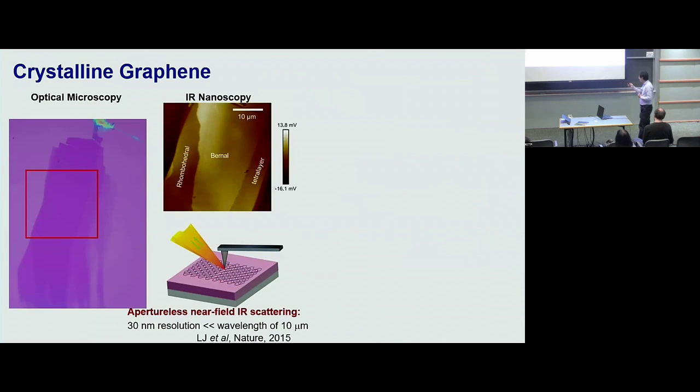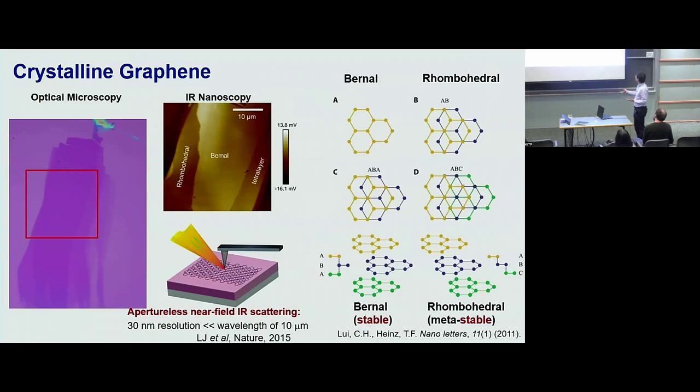And these are 2 different stacking orders of graphite, right? Specifically, the Bernal stacking corresponds to the so-called AB, AB, AB stacking. There are just 2 positions when you stack layers on top of each other. All the even layers are aligned. If you look from the top, all the layers are aligned, but they are shifted. Well, there's another stacking order that we also got from here.